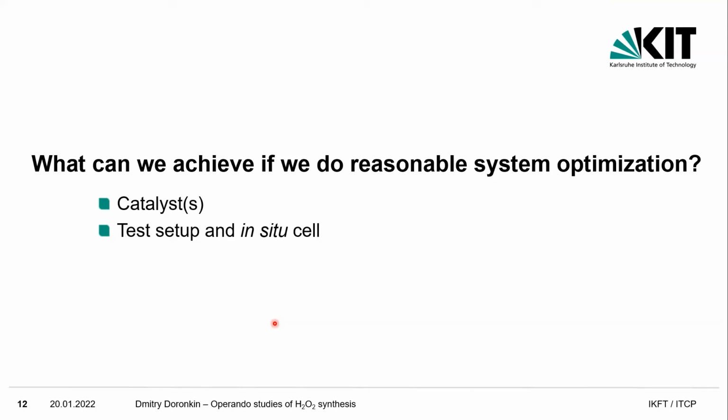Yeah, Dmitry, an interesting possibility to determine the size while you do these experiments is by using hydride formation as the probe, because the type of shifts and the corresponding occupancy of hydrogen scales up with the particle size. We showed that in 2013, it was 1 year before Bugayev's paper, but it's just a cool method of determining the particle size while you do this type of work.